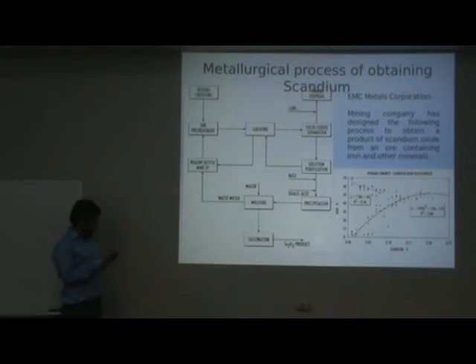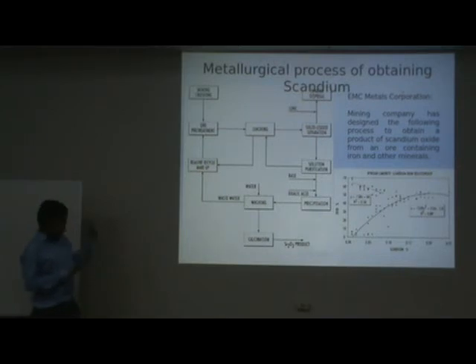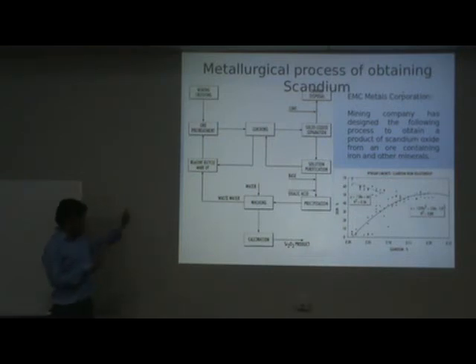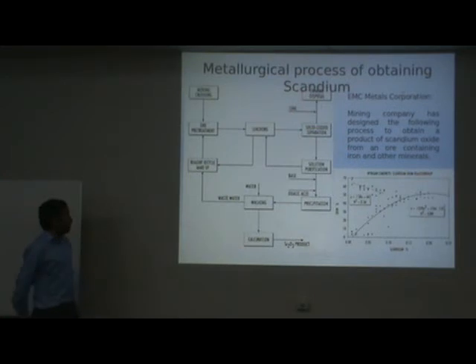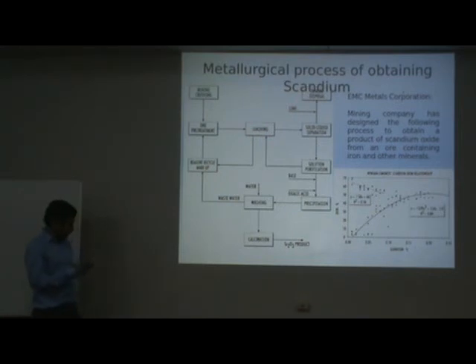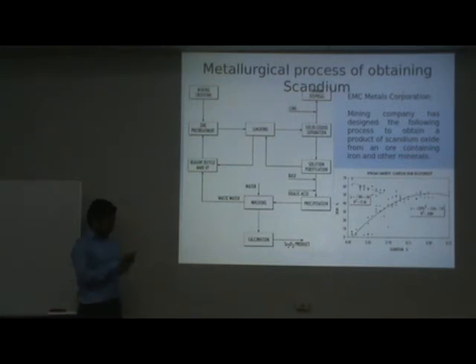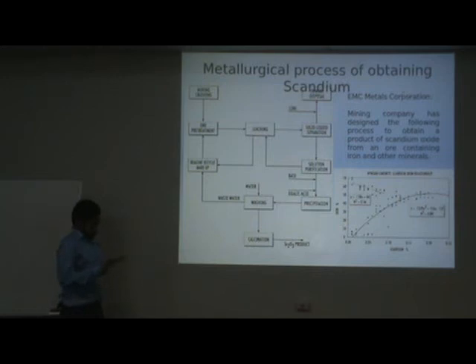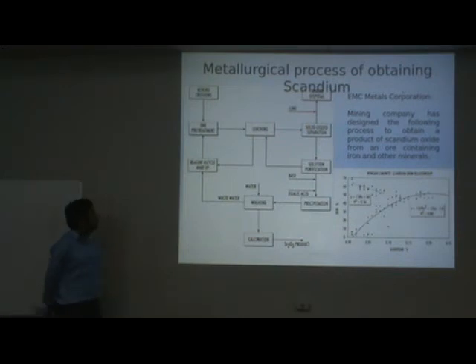For the first stage, fluoride can also be added in various forms to the ore. Sulfuric acid is used in the leaching process; fluoride acid or nitric acid may also be used. The leach liquor is then separated from the solid using specialized filters in a solid-liquid separation process.